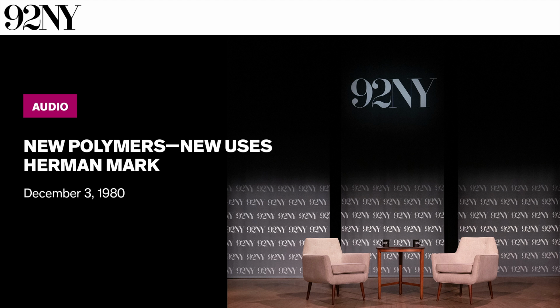And these pipes really are nothing but carbon. There's a little bit of hydrogen, very little hydrogen in it. And these pipes, you can hear that they are very hard. You have seen that they never melt. And of course, being carbon, they are not attacked by any chemical ingredients. And they are used, for instance, in atomic energy plants to pump the liquid sodium around, or they are used in plasma physics for the walls of containers which can stand 4,000 degrees centigrade temperatures of this type. Every metal would not only be molten, most metals would actually vaporize under such conditions.